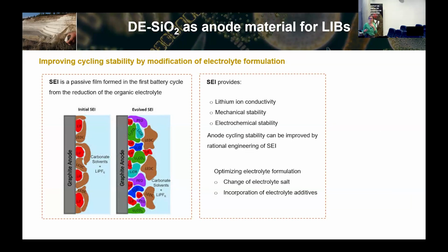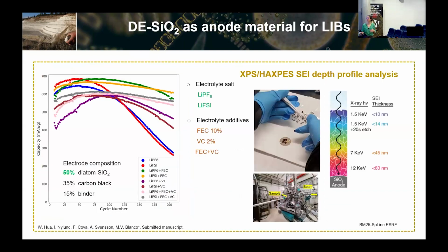So a typical thing you can do is to try to optimize electrolyte, salt, and additive. So we didn't take much risk. We just tried LiPF6, that is the standard one, and LiFSI, which normally works for silicon. And we play a bit with some additives, FEC, VC, and FEC VC, which is normally what industry uses. And then we did the same cycling. And then we can see this is the typical behavior we had before, LiPF6. With LiFSI, we have very similar capacity decrease trend. And we can improve a bit the capacity after 200 cycles if we have some FEC addition to the electrolyte.